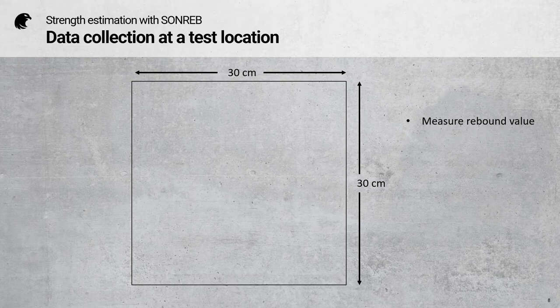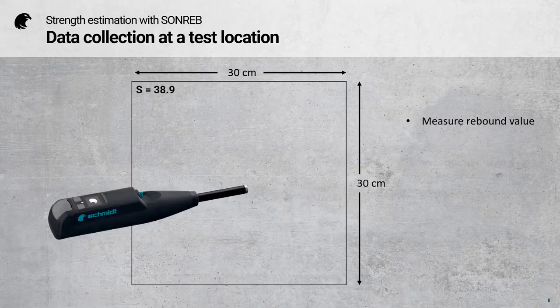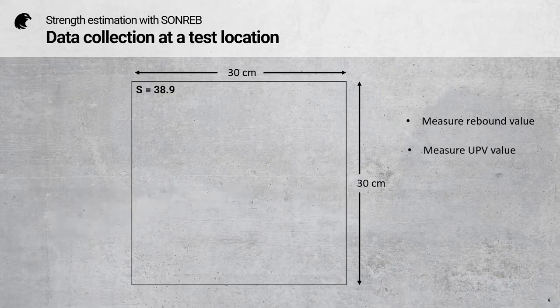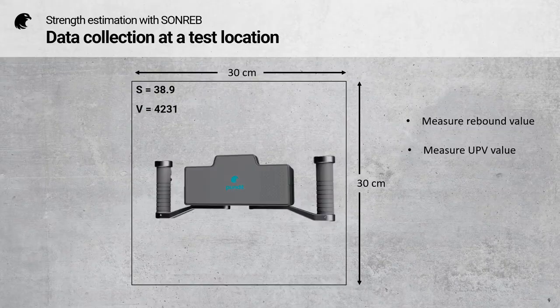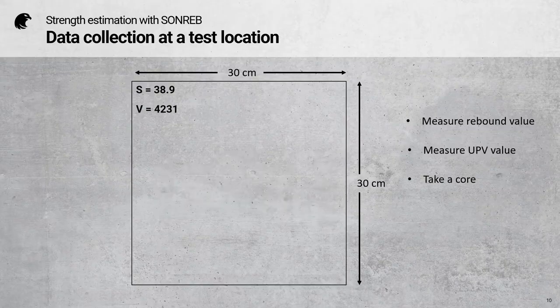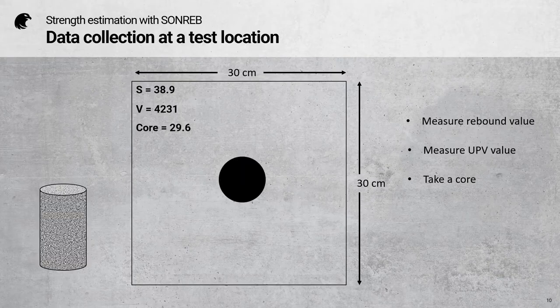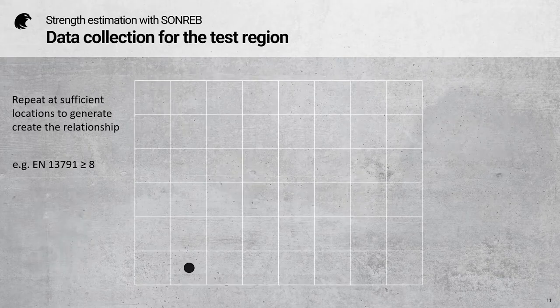Taking it step by step, we first define our test location. In the European standards, this should be approximately 30 by 30 centimeters, and we measure the rebound value. Now at the same test location, we measure the ultrasonic pulse velocity. And the final step is to take a core and determine the core strength. And then we repeat this at sufficient locations to generate the relationship. In the European standard, we need at least 8. And now we should have sufficient data to generate the coefficients.